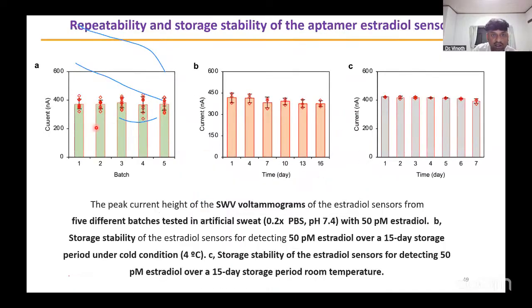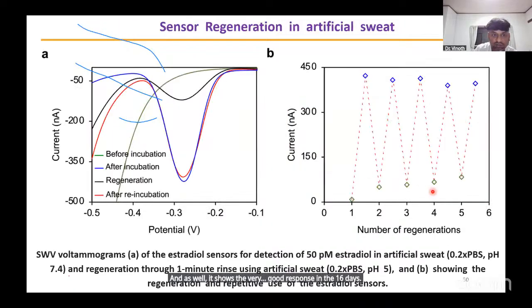Also, the repeatability and storage stability of the aptamer estradiol sensor. The peak current height of the square wave voltammograms in the estradiol sensor from the 5 different batches. It also shows very good batch to batch variation, and also it shows very good response in the 16 days. And also the sensor regeneration.